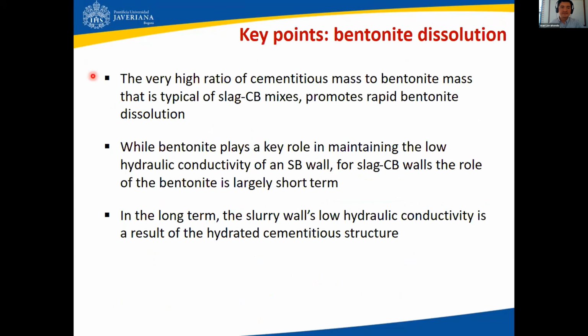So to us, the key points to take here from this first point of bentonite dissolution, and perhaps the implications that it also has, is that the very high ratio of cementitious mass to bentonite mass that I mentioned earlier, about 2.5 for slag CB systems, that is typical for these mixes, promotes rapid bentonite dissolution. And that again has to do with a very chemically aggressive environment that takes place there.